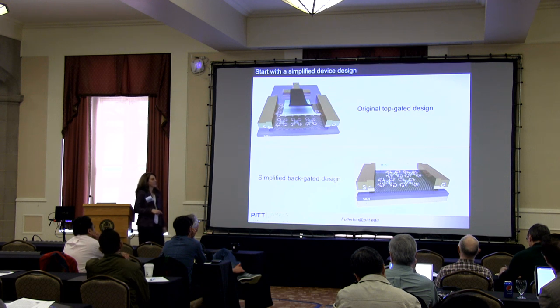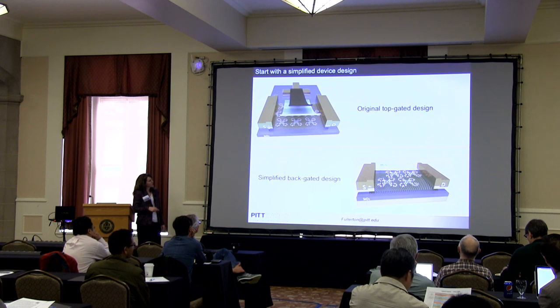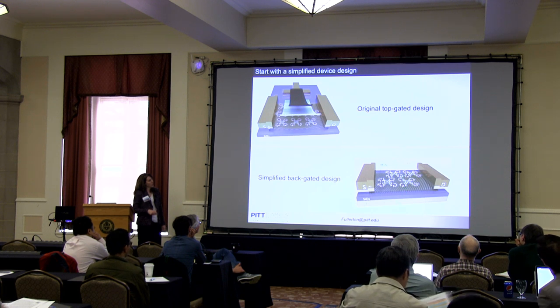But the problem was when he reads at 0 volts, he has to read at a voltage that's not going to disturb the state, and he has a terrible on-off ratio. So he said, okay, let's try a 2D crystal that's ambipolar, with a threshold voltage of one of the branches close to zero. And so he started doing this work more recently on WSe2.